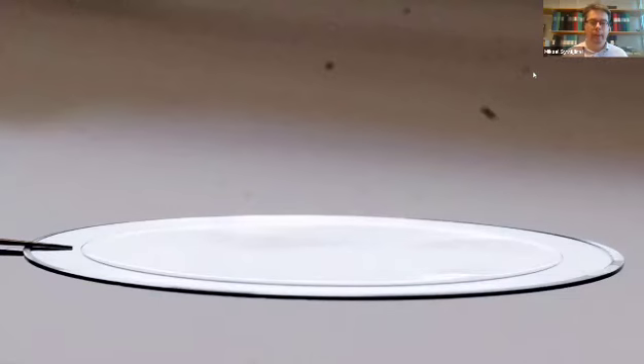So that we managed to do. So here you see about 100 micrometer thick layer of silicon carbide. And surfaces are smooth, and if we look into the quality of the material, XRD and photoluminescence and some other things, then it shows that really it's nice quality. And that was one of the activities in my PhD thesis, which I presented in 1999.